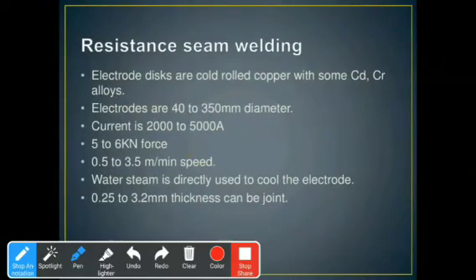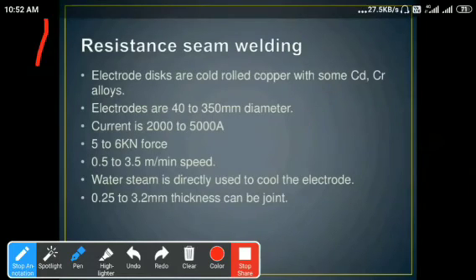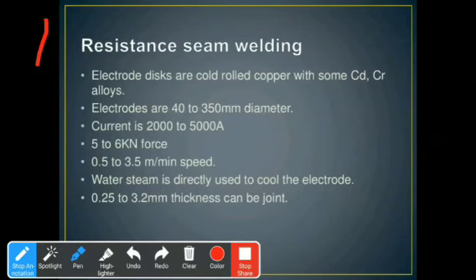So this is the resistance seam welding description. This is cold rolled copper with some cadmium chromium alloys. Electrodes are 40 to 350 mm diameter, and the current is 2000 to 5000 amperes. The force may be 5 to 6 kilonewtons, and the speed of that particular workpiece is 0.5 to 3.5 meters per minute, and a water stream is directly used to cool the electrode, and